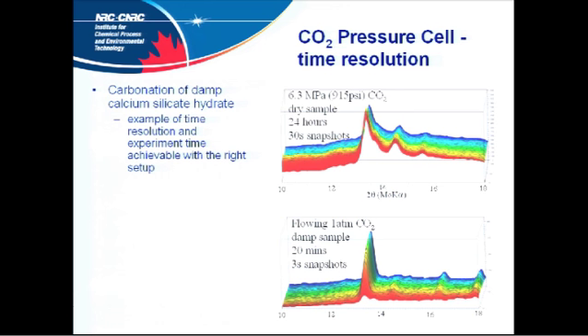a blank experiment, really. This was supposedly a very CO2 sensitive material. This was just slightly sub-supercritical, so 915 psi CO2, 24 hours. These are basically static snapshots, 30 seconds, and it does absolutely nothing. It just sits there, very boring. And it's one of these things that comes up. If you make the thing wet, this happens.